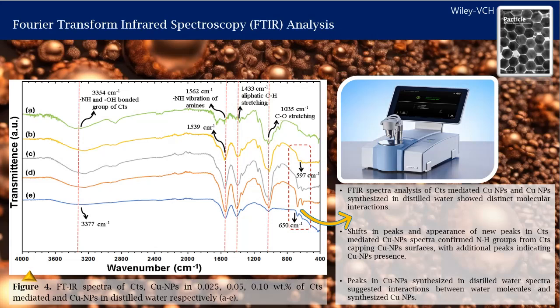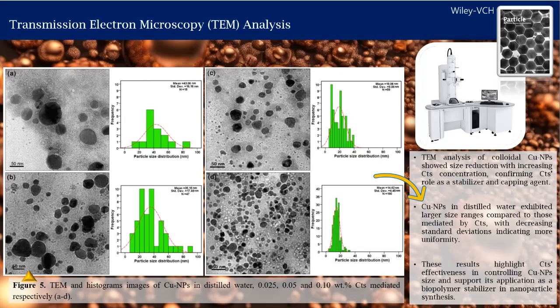with distilled water synthesis. Fourier transform infrared spectroscopy analysis reveals distinct molecular interactions in chitosan-mediated copper nanoparticles and those synthesized in distilled water. Shifts and appearance of new peaks in chitosan-mediated spectra confirm NH groups from chitosan capping copper nanoparticle surfaces, with additional peaks indicating copper nanoparticles presence. Peaks in distilled water synthesized spectra suggest interactions between water molecules and copper nanoparticles.